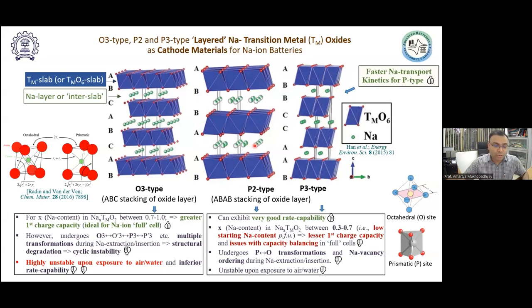So now, in a nutshell, to summarize, the P-type structure has an advantage of sodium ions having faster transport. That is, it can lead to a higher rate capability, whereas the O3 type of structure would lead to a sluggish sodium transport and hence poor rate capability. However, the O3 type of structure has a greater sodium content to start with, up to 1 per formula unit. And as we know that in an alkali metal ion cell, it is the cathode material which is the reservoir for the sodium ion. Just like the cathode material is a reservoir for the lithium ion in a lithium ion cell. So considering that the cathode material is a reservoir for sodium ion, it is good that this structure can have 1 per formula unit of sodium ion to start with.